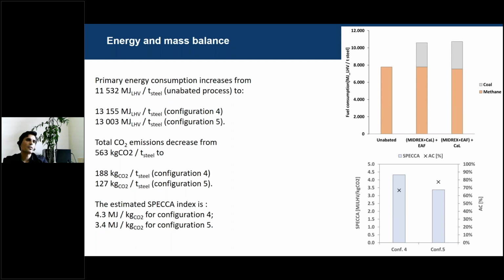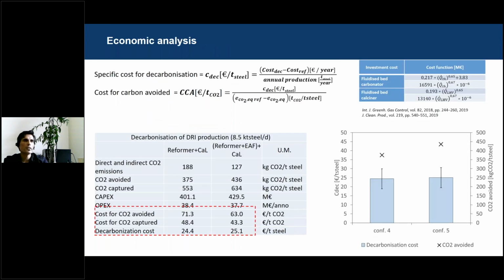because for configuration 4 we have 4.3 megajoule per kilo of CO2. Instead, for configuration 5, which is the most integrated solution, the SPECCA is lower. So it means that the last configuration seems to be a very efficient configuration. Again, for the economic analysis, the cost of CO2 increases a little bit. The CO2 avoided is greater, more than 60%.